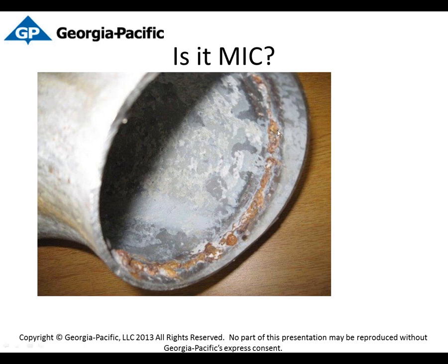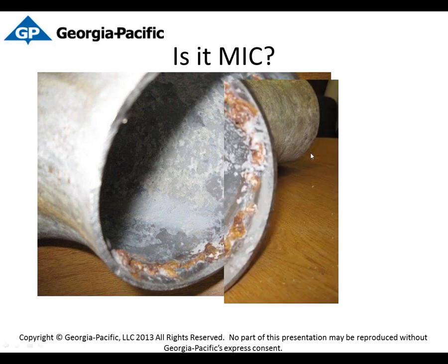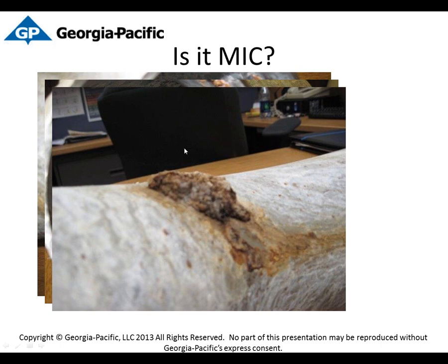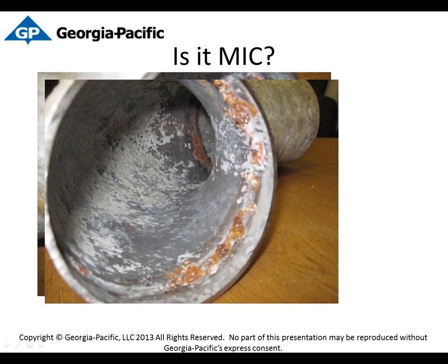So this is what we began to see on our piping systems on the inside. Actually, what we saw at first was just like the other mills. You see localized corrosion on the external of the piping system, and you wonder, what's going on there? And then you wait till an outage and actually go inside the piping system when it's time for the inspection. And what you saw on the weld line here was found. We thought, we've got MIC here too.